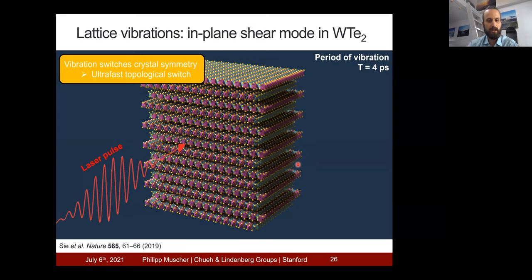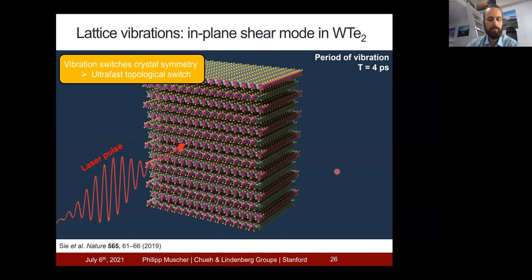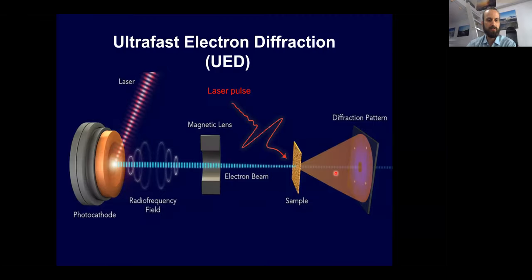So I wanted to understand how this vibration changes as we insert lithium into the van der Waals gap between the layers. For this, I turned to a technique called ultrafast electron diffraction. We have our tungsten ditelluride sample located over here, and we shoot a laser pulse on this material to launch that vibration. Then at a well-defined time delay, we shoot an electron pulse through the material. The electron pulse interacts with the atoms and diffracts off them, and we can collect a diffraction pattern that informs the crystal structure of the material. So we can control the time delay between the laser pulse and the electron pulse to map out on ultrashort timescales how the structure of the material is evolving.